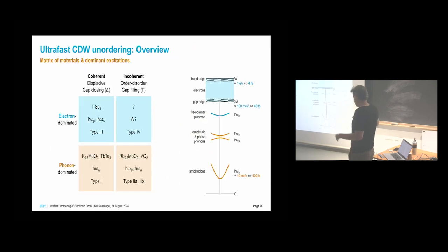Okay, and now I give an overview of what will come. So I will have this matrix. I will look at electron-dominated charge density waves, excitonic insulator type things, or phonon-dominated, the classical Peierls. And then I will make a difference between a coherent displacive process where you have coherence in your system and, let's say, every atom moves the same way, or you have an order-disorder type transition indicated by the gap filling, and this is incoherent.